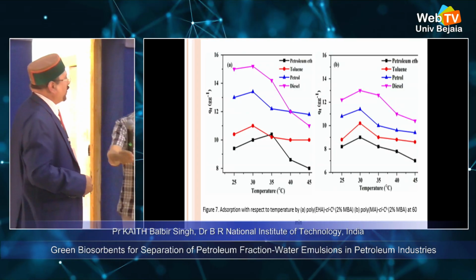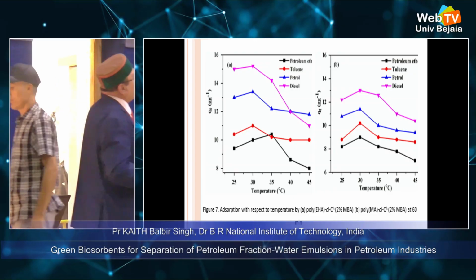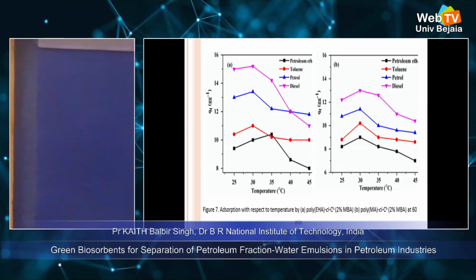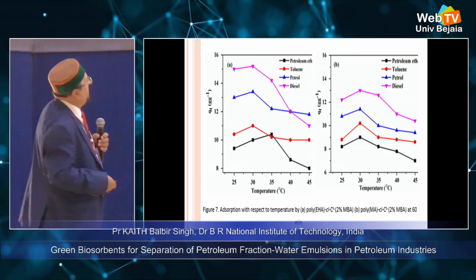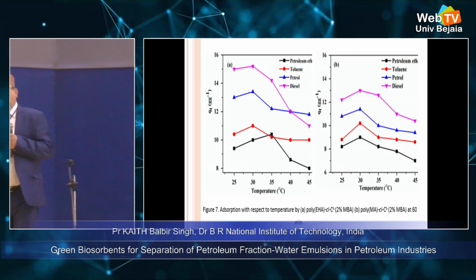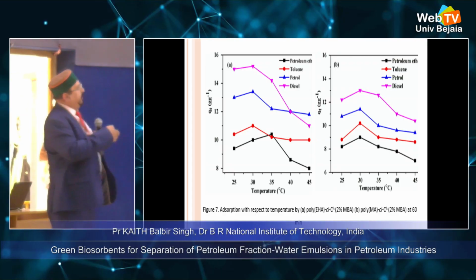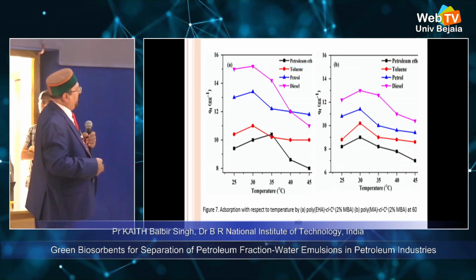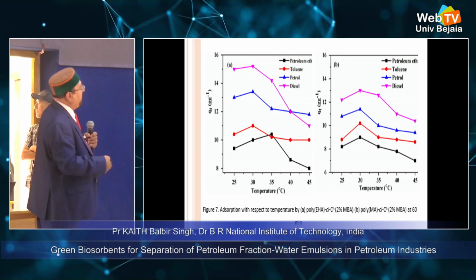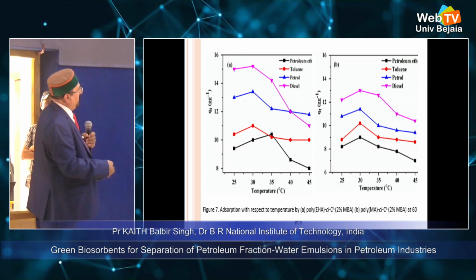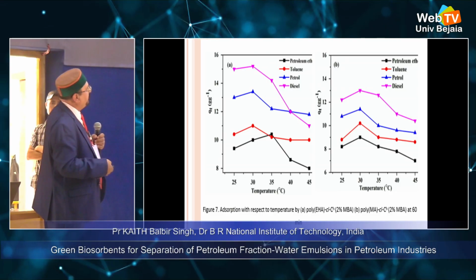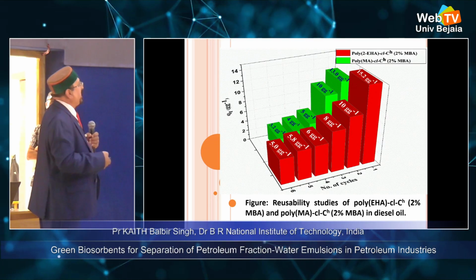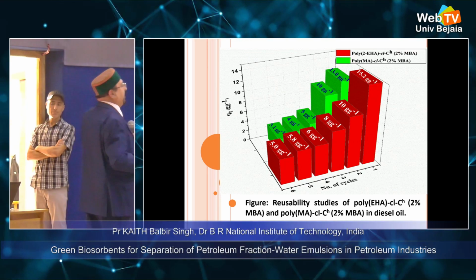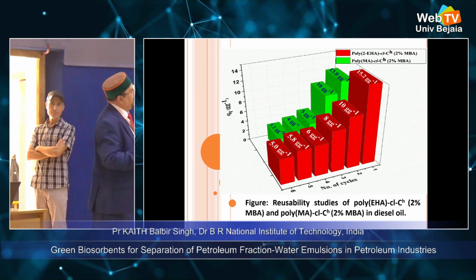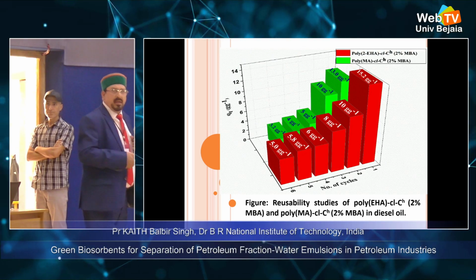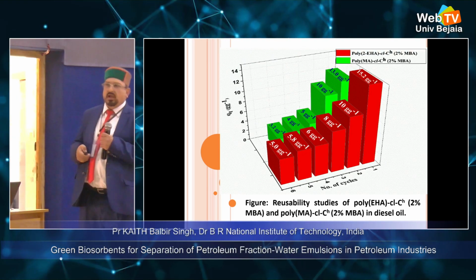And we also studied the impact of temperature and the time for the separation of different oil fractions using this hydrophobic material, and we got better results with the petroleum at 30-degree temperature. So these materials can be recycled up to 6 times. You can see for yourself, and they are highly effective in the cleanup of the oil fractions from the water.